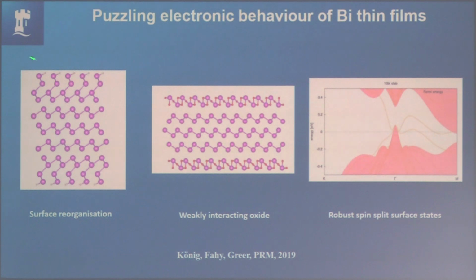The first thing is if you form, this is DFT calculations on the structure. This is the 111. This is the normal direction. If you look at growth direction this way, this is what normally happens. You get these bilayers. But if you put a covalent bond up at the top to try to remove anything happening at the surface, the electronic structure at the surface, you get a reorganization. What happens then is you get this very weakly bonded structure down here, but the surface states just exist here now.